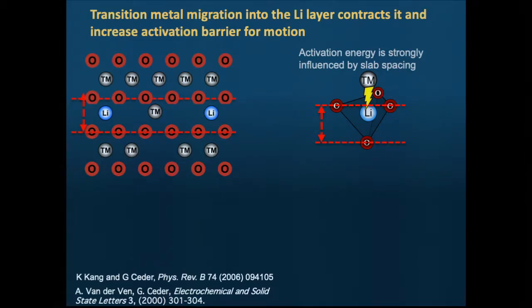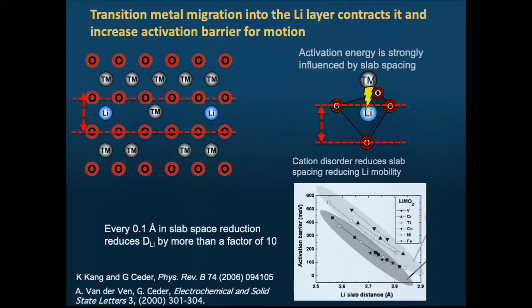So you cannot charge and discharge your battery at a reasonable rate. You can back that up with ab initio calculations, where we actually can artificially control the slab, and what you see is the activation energy goes up dramatically as you contract this slab.